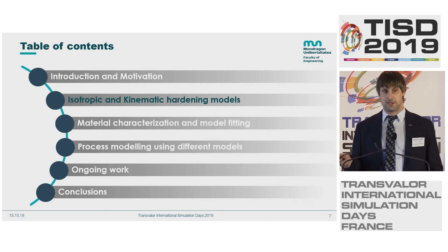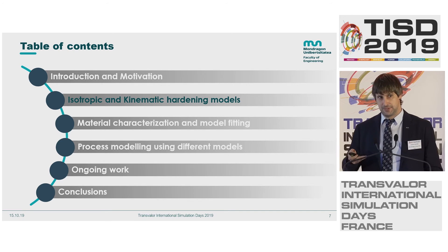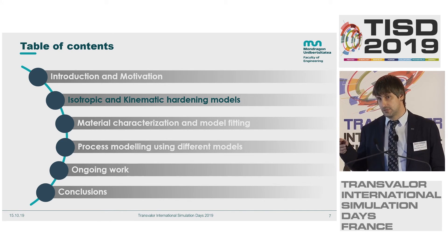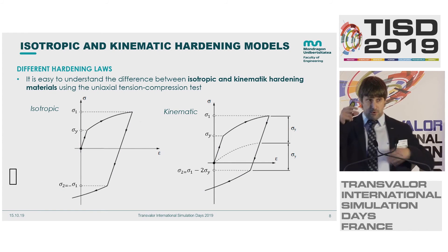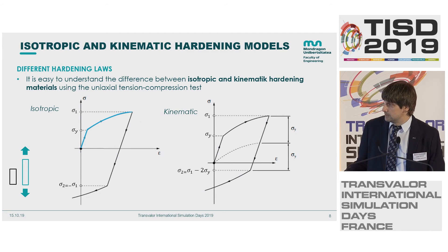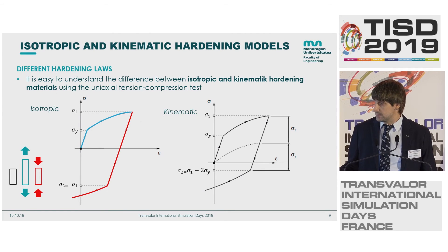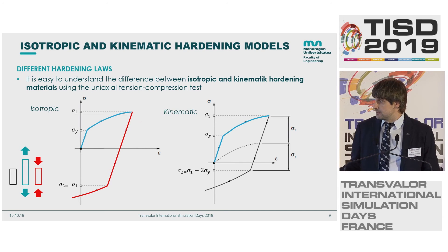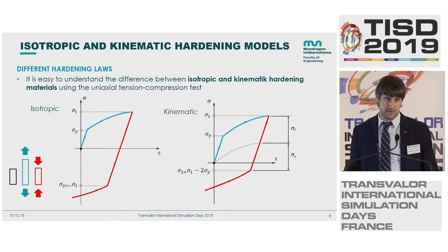Let me explain what isotropic and kinematic hardening models are. When you load a material and compress it in a uniaxial state, in isotropic hardening you need to go to minus sigma_1 to plastify. In kinematic hardening, you go to sigma_1 but you only need to go two times the initial yield stress to re-yield.